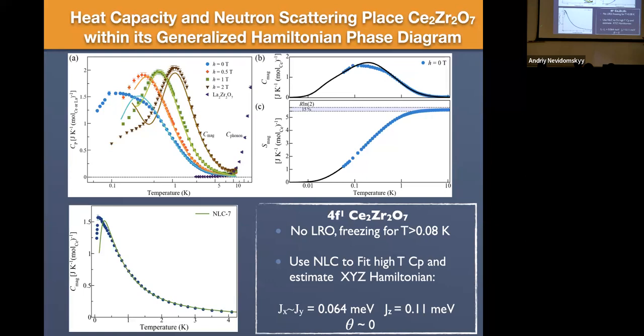And in fact, the argument that we did make in one of our papers, and this is just an observation, is that if you take the heat capacity from the peak in our measurements, which is right there, and you integrate that up, you actually get the so-called Pauling entropy, right? In classical spin ices, you have this missing entropy at low temperature, and the missing entropy is the difference between R log 2 and what you get if you order all the tetrahedra up into 2 spins in, 2 spins out, but you don't do anything else. This is famously calculated by Pauling for proton disorder in ice, and you get that with a plateau in the heat capacity. Here there's no plateau, but if you go from the peak, you still get that result.